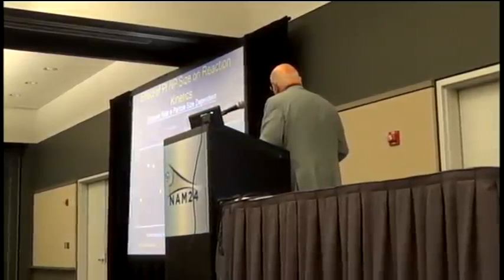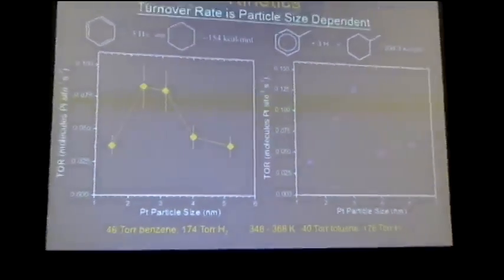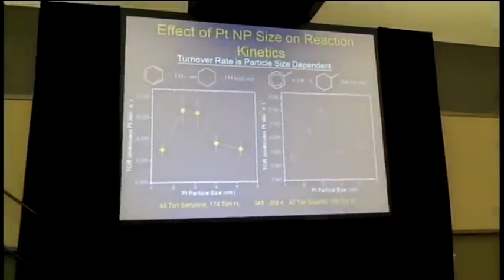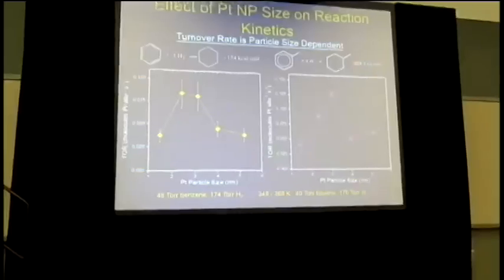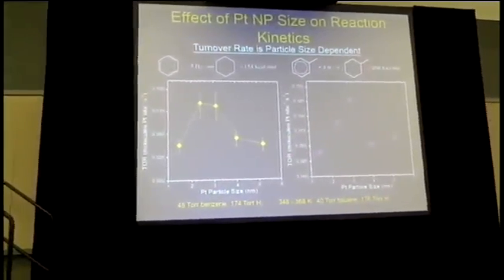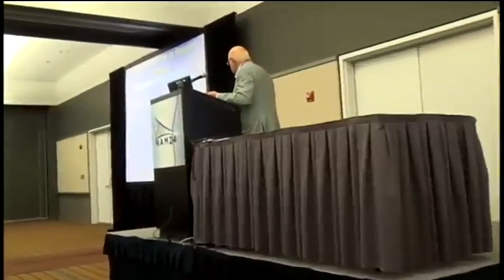So what we find with this product distribution, and my postdoc, who is now a great industrial scientist, Pushkarev, found that as you change the particle size, you can change the test reactions which are used for most oil companies, benzene hydrogenation or toluene hydrogenation, by a factor of 4. And this means $100 million a day for making high-octane gasoline. But in fact, the size dependence of the turnover rates were crucial.